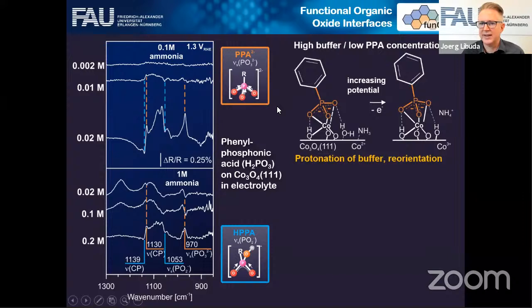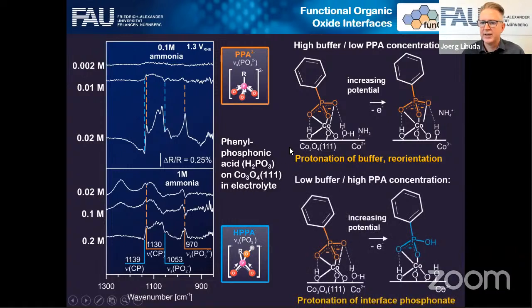So what you find out in the end is that as a function of the potential at low coverage, these molecules basically change their orientation as a function of the potential. Whereas at high coverages, what you see is a protonation, a partial protonation of the phosphonic acid, but still the molecules remain attached to the surface with two legs, and you're not going to lose it from the surface, even if you lose one leg, two legs are enough to stand on the surface. So this is the big advantage with this phosphonic acid anchor.